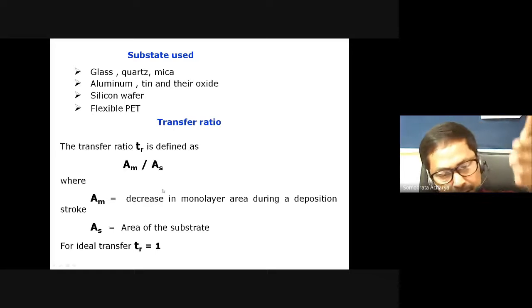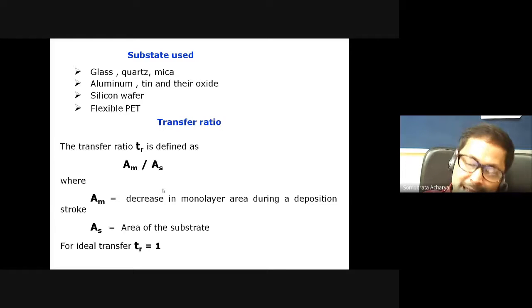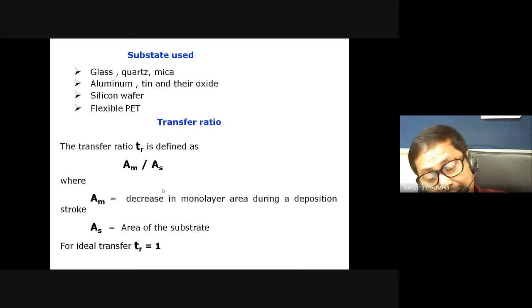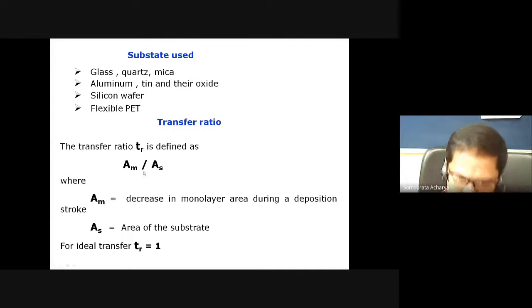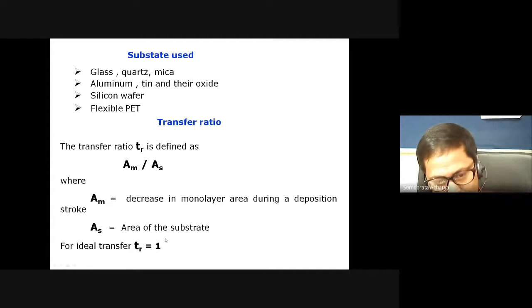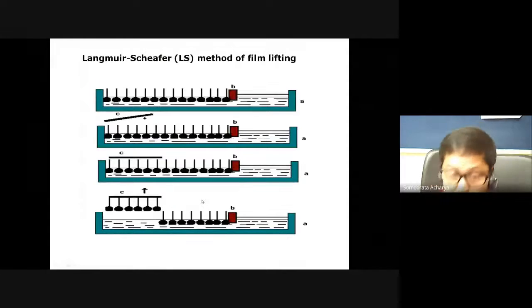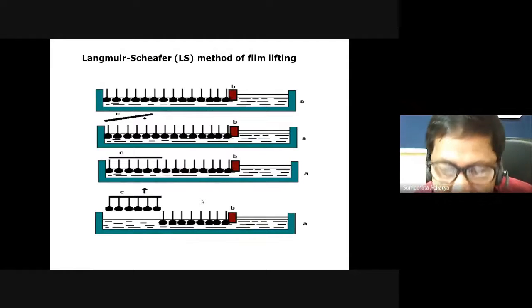Because once you are lifting some set of molecules from the air-water interface, that area becomes void, and the molecules that will be transferred onto the solid substrate will depend on the subset of the area. That's why it is a ratio, and for perfect transfer of these molecules or nanomaterials, this transfer ratio should be 1. That means whatever you are transferring onto the solid substrate will be equal to the area of the solid substrate. Okay, so this transfer ratio is a very important parameter to measure how your film is transferring onto the solid supports there.